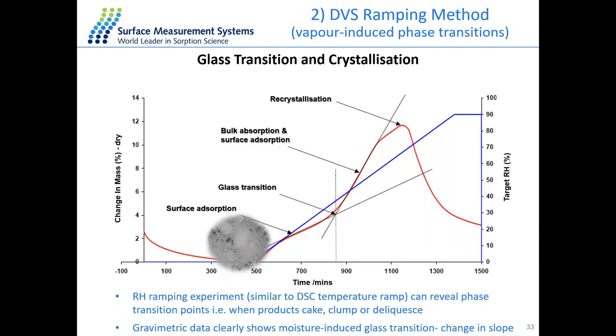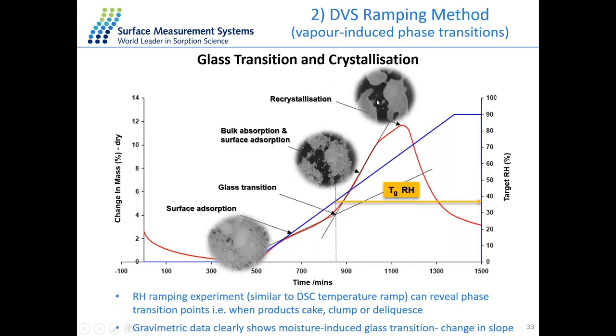We can also couple it with the camera. In this case, we have our starting material, and when we introduce relative humidity, we start having a bit of surface adsorption. However, when we come to this area here, we start to see a few changes in our sample. This is in relation to the glass transition of the material. Now the molecules are interacting more with the bulk of the material and changing the bulk properties. So we can then understand what relative humidity is responsible for this glass transition stage.